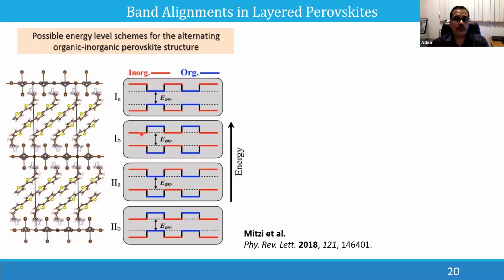So if the valence band maximum and conduction band minimum, the top one is the conduction band, and the bottom one is the valence band. If the valence band maximum and the conduction band minimum are contributed by the organic component, then it is a type 1A material. Normally type 1A you won't get in perovskites. Normally the inorganic part will define both the valence band maximum and the conduction band minimum, like this.